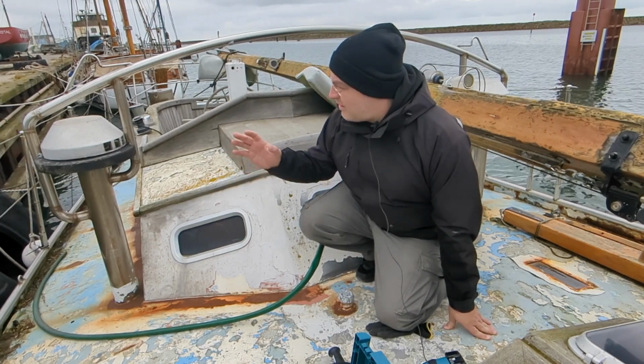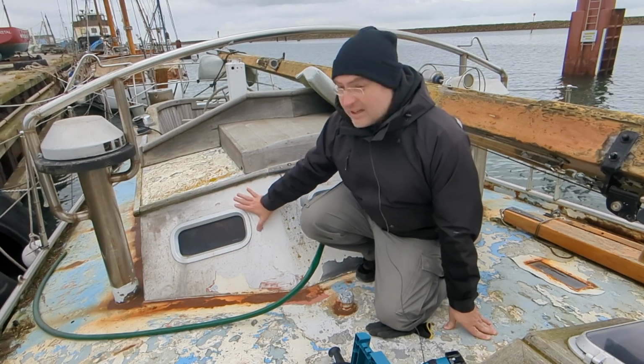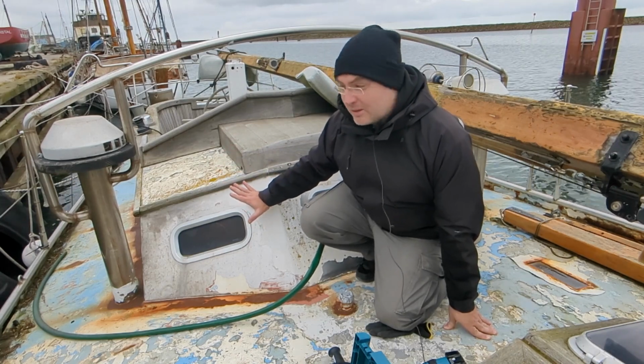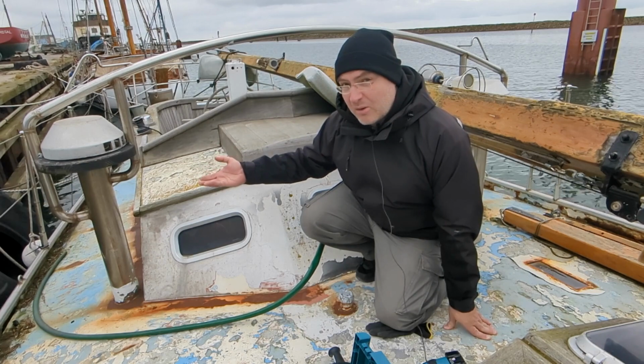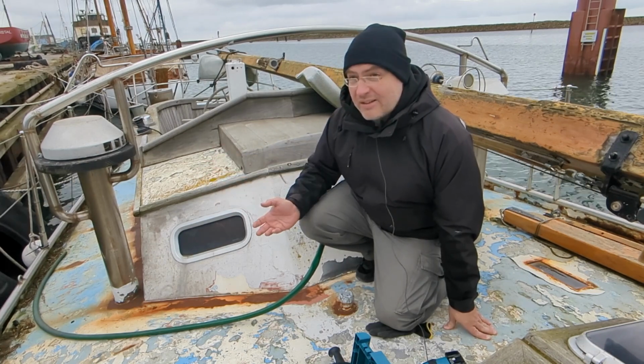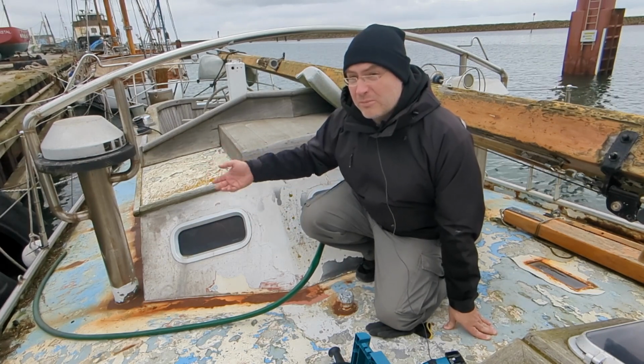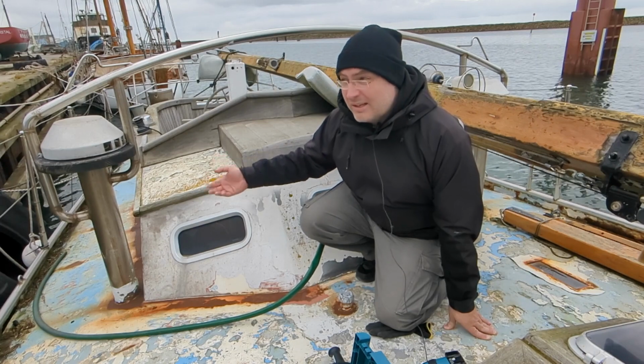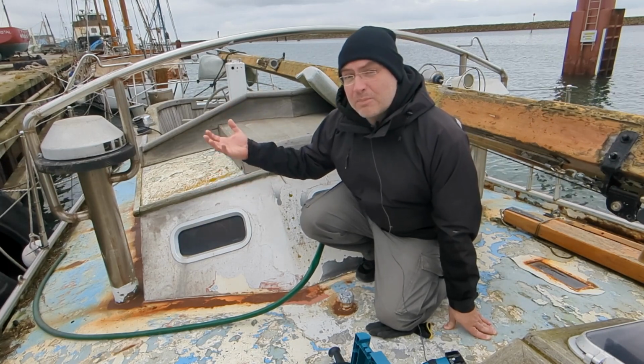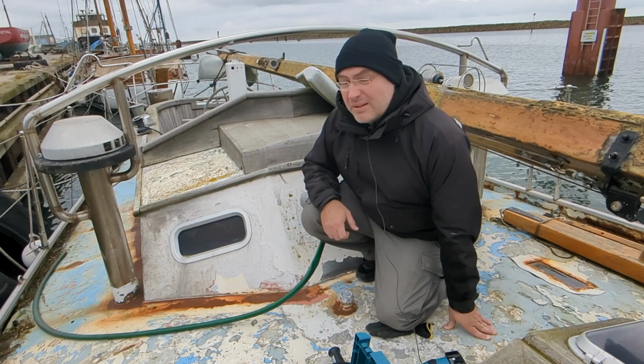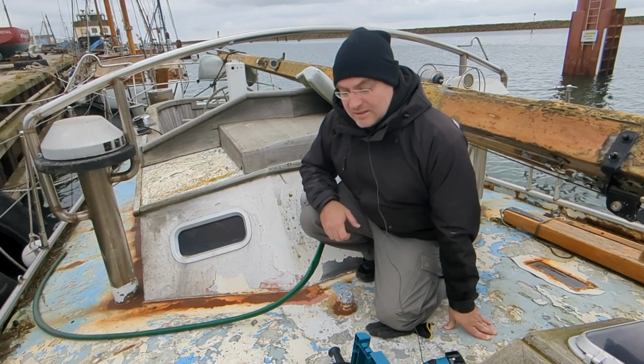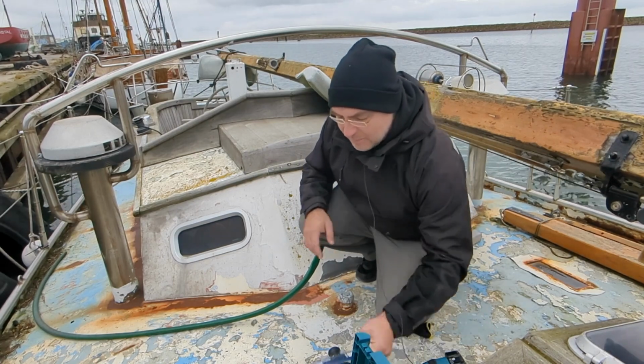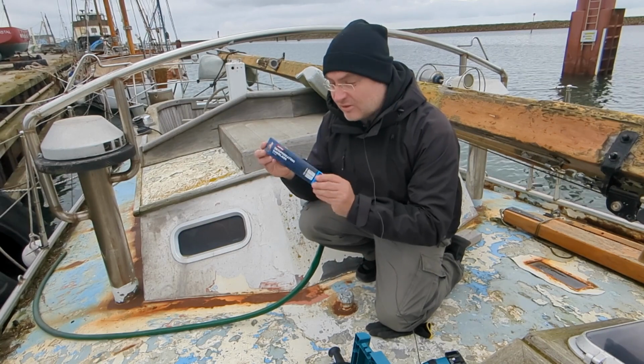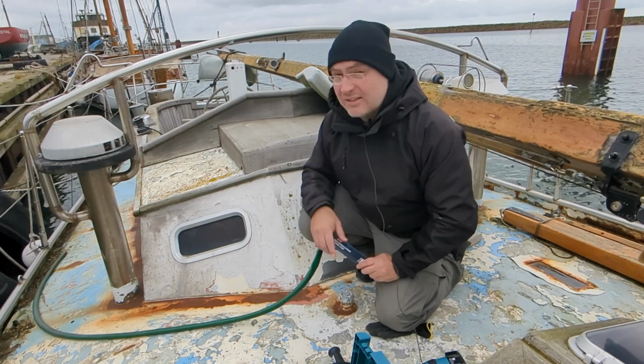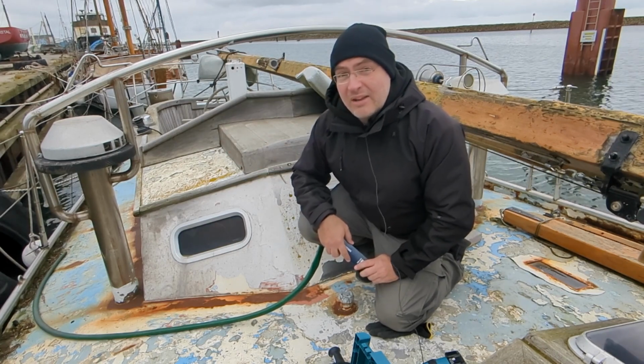And the main problem with stainless is when you weld it, and I'm not going to weld it, but those sparks that are coming off from the grinder, they're fairly hot and they can form hexavalent chromium. We are in the open air, it might not be too big of a problem, but I'm not willing to chance it. So instead, I bought some blades for the reciprocating saw that should be able to cut stainless, and then I'm going to cut it away that way.